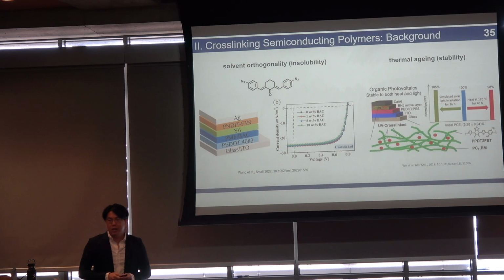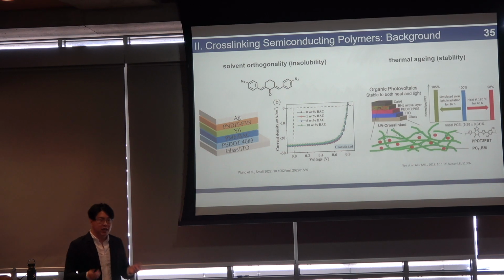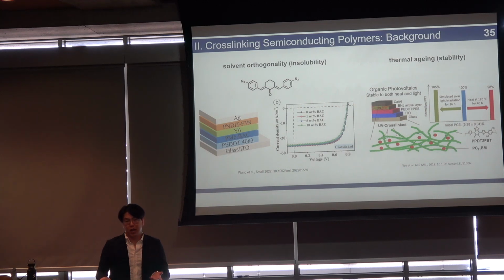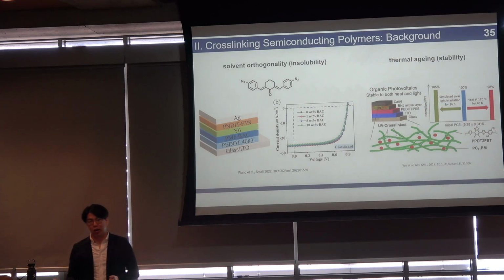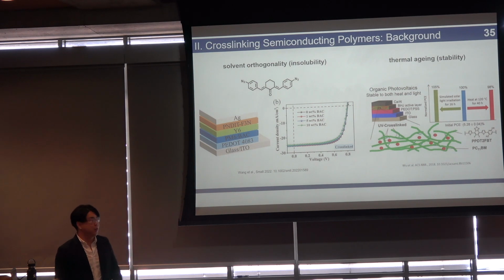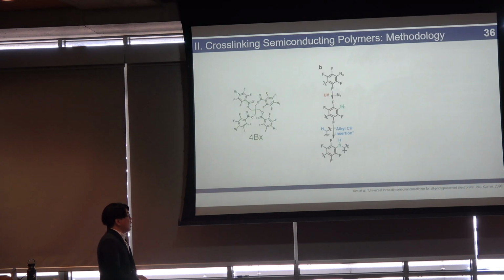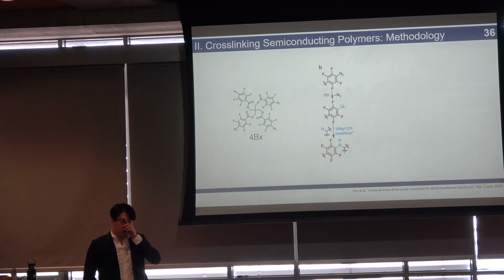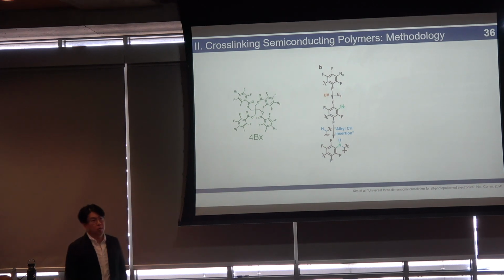The other reason why this has been explored is because when you freeze the morphology, it becomes more stable, especially to thermal aging. So your solar cells can survive longer and they can be heated to a higher temperature with better stability. So to look at the cross-linker that we used, in 2020 there was a Nature Communications paper published from KAIST, and they reported this 4-armed azide cross-linker, where there's 4 cross-linking sites at each of these armed branches.